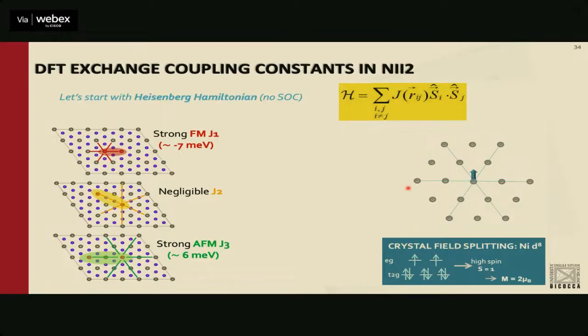And I have a triangular lattice. Nickel I2 has a triangular lattice. So now let's try to place our spins so that they satisfy these interactions. My first J1 is ferromagnetic, so I place my first shell to be up. Then I have a strong anti-ferromagnetic J3, and so I place them down. But you immediately see that then this interaction is not happy, right? Because this one would like to be ferromagnetic. So you have exchange frustration, and you expect non-collinearity, right? You have a system that cannot satisfy all the exchange interactions at play.